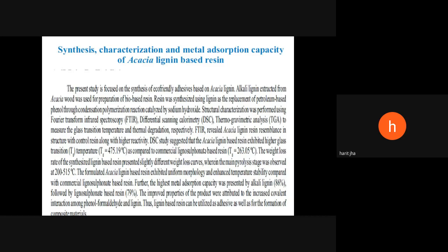Further, the highest metal adsorption capacity was presented by alkali lignin, followed by the lignosulfonate-based resin. The improved properties of the product were attributed to the increased covalent interaction between phenol, formaldehyde, and lignin. Thus, the lignin-based resin can be utilized as adhesive as well as for formation of composite material.